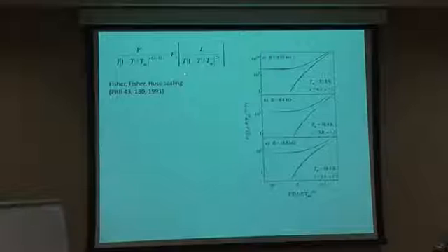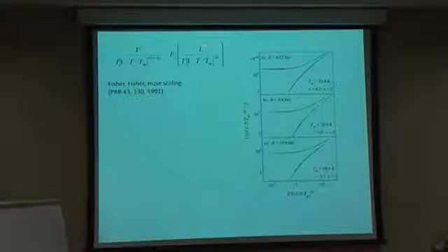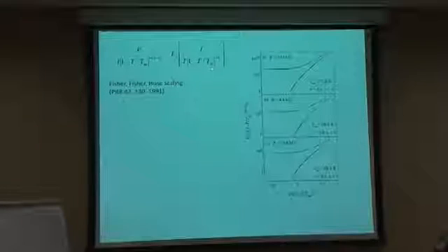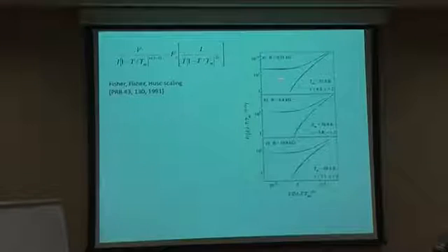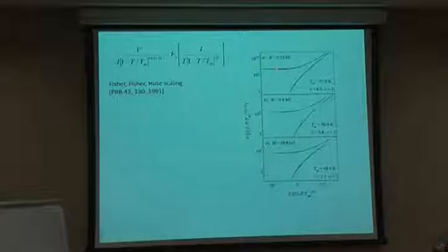So what we do, we transform voltage into this relation, current into this relation, and put all our IV curves at all temperatures, and all of the IV curves which are in the vortex liquid phase will collapse on a single universal curve, and all our IV curves which are in the vortex solid phase will collapse on another universal curve.